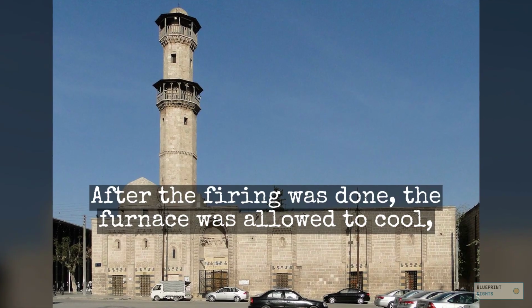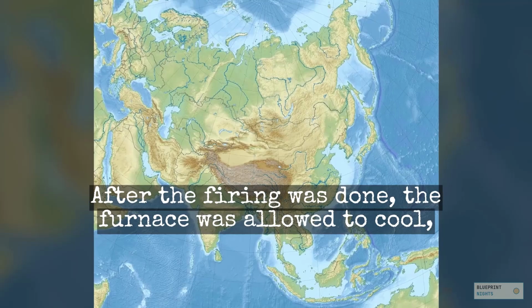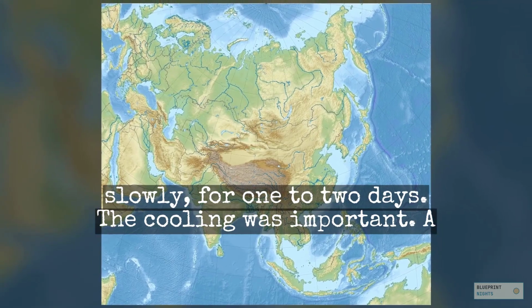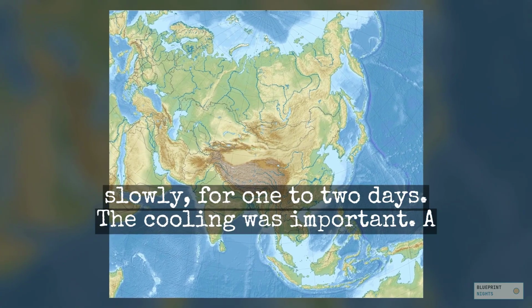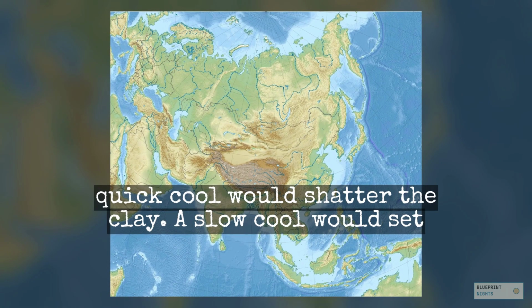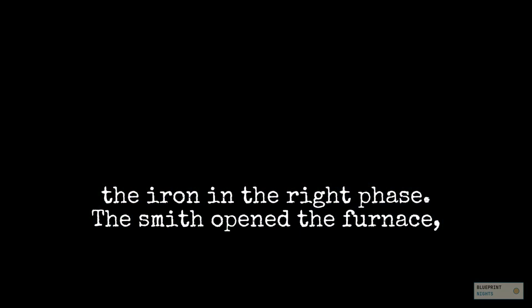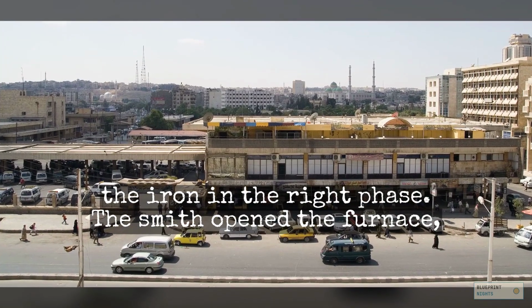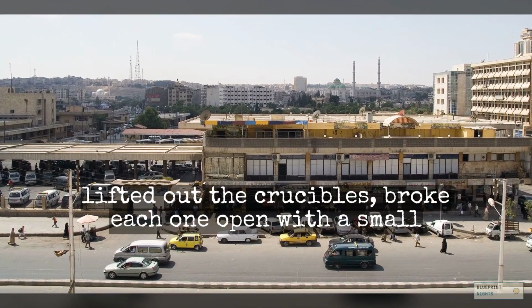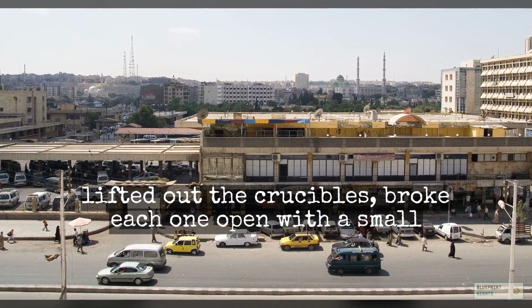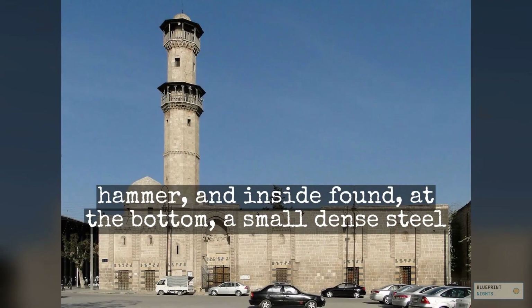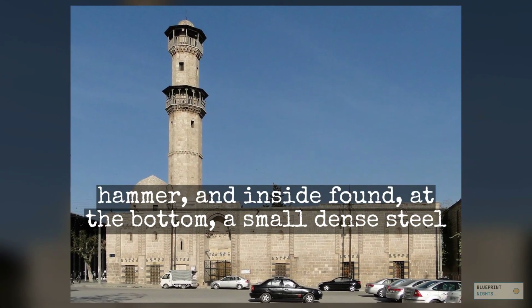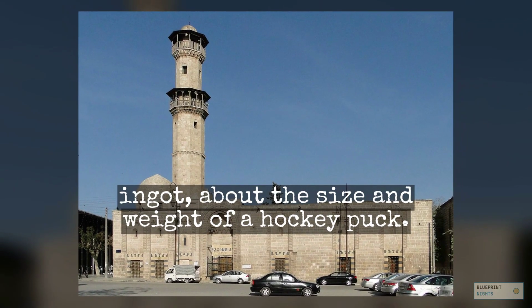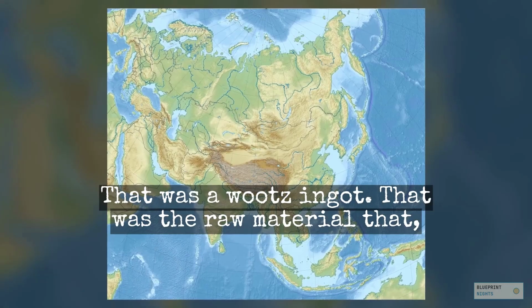After the firing was done, the furnace was allowed to cool slowly for 1 to 2 days. The cooling was important. A quick cool would shatter the clay. A slow cool would set the iron in the right phase. The smith opened the furnace, lifted out the crucibles, broke each one open with a small hammer, and inside found, at the bottom, a small dense steel ingot, about the size and weight of a hockey puck. That was a Wootz ingot.